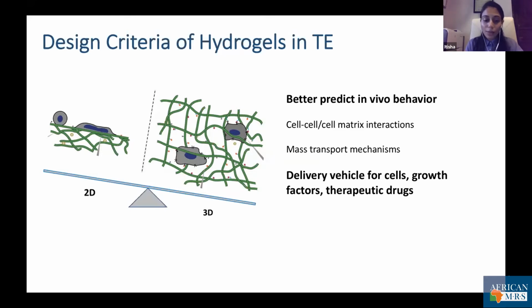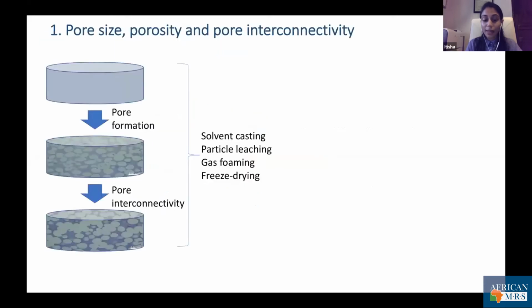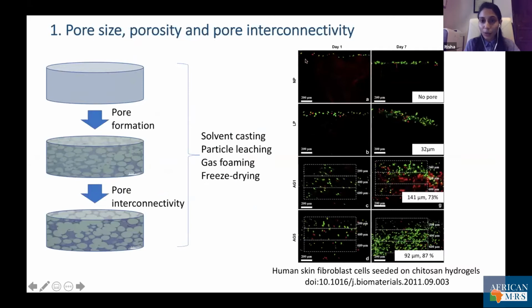Now, the physicochemical properties of hydrogels play an important role in cellular behavior. To start with, pore size, porosity, pore interconnectivity. Different techniques are used to render these hydrogels porous, as for example, solvent casting, particle leaching, gas foaming, freeze drying. And freeze drying is mostly used to improve pore interconnectivity, which is important for cell culture. This is an example of a cell grown onto chitosan hydrogels, porous chitosan hydrogels.